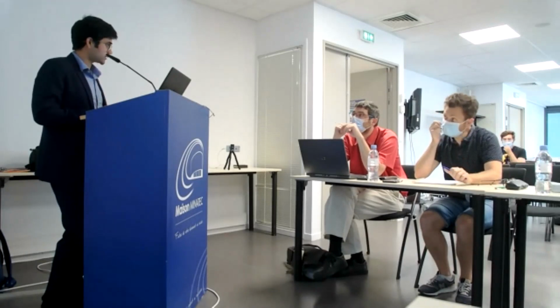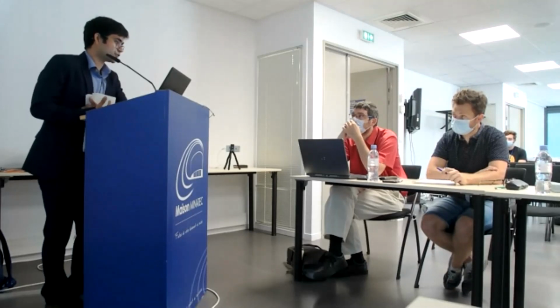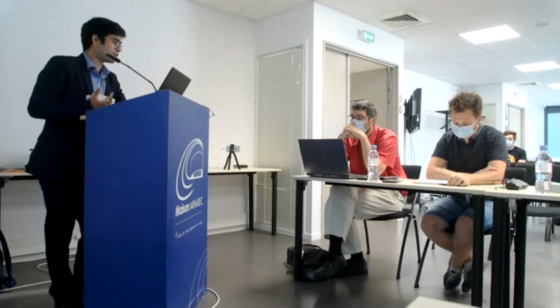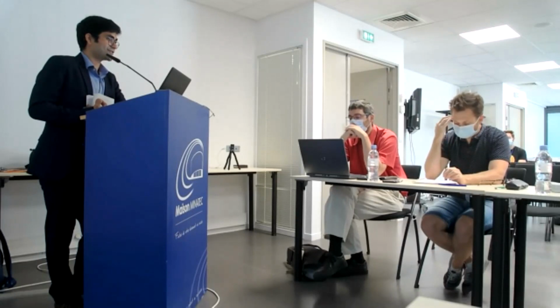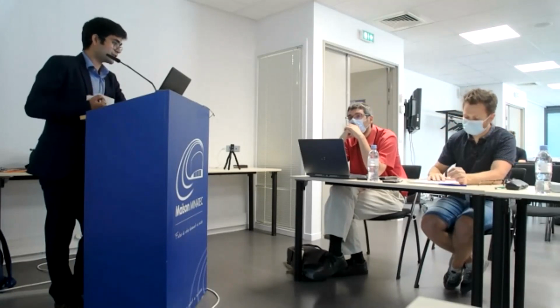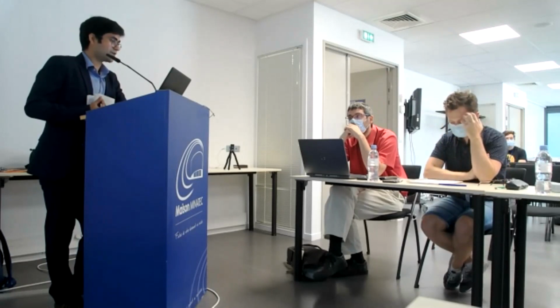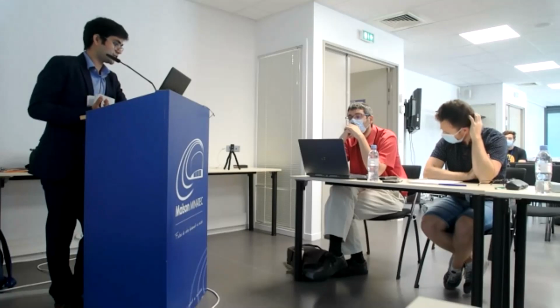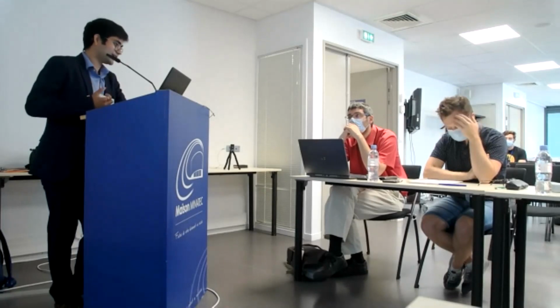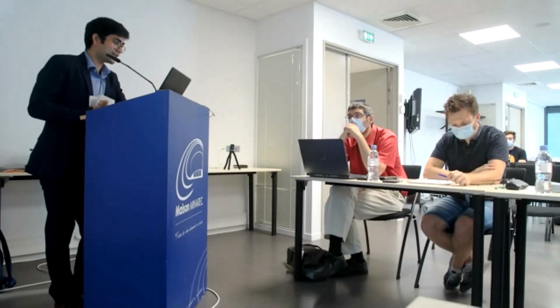The third point I can mention is the estimation of the coalescence solid fraction. In our entire work, we relied on the work of Iliane Giroux, which was done during welding. In the welding, she did tensile experiments in the mushy zone for a very low cooling rate, for instance 80 Kelvin per second, which is far from the cooling rate in L-PBF, where we have around 10⁶ Kelvin per second. So this is a very strong assumption: based on the cooling rate, we thought the coalescence solid fraction might not change. To estimate the real coalescence solid fraction of the alloy in L-PBF conditions, we might need experiments reaching that cooling rate and do tensile experiments at that cooling rate. So it's very challenging to do.